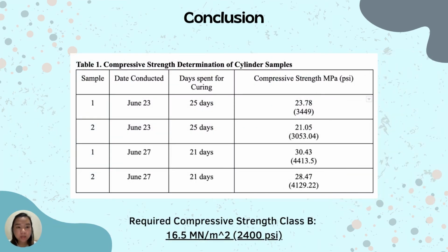So, to conclude this experiment or video presentation, we have here two tables prepared so that we'll be able to compare the required compressive strength and flexural strength easier to the data. First we have here table 1, which is compressive strength determination of cylinder samples. We have the first two samples conducted on June 23, which spent 25 days for curing. We have 23.78 for the first sample and 21.05 for the second sample. For the next batch, June 27, which is 21 days spent for curing, we have 30.43 and 28.47.